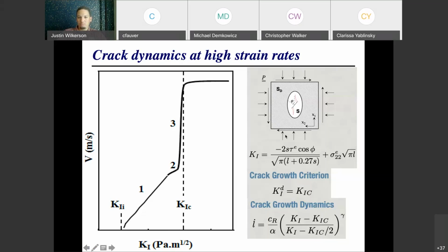If you remember anything from fracture mechanics, there are formulas and tables by which we calculate stress intensity factor as a function of the geometry of the body, the geometry of the crack, and the applied stress state. Okay. One important thing to remember about the stress intensity factor is that it's a function of the crack size itself. Here I'm using L to denote the crack size, and S denotes the size of a flaw from which that crack nucleated. And so you can see in this term here, I have that typical square root of the crack size dependence that we always see in the stress intensity factor.